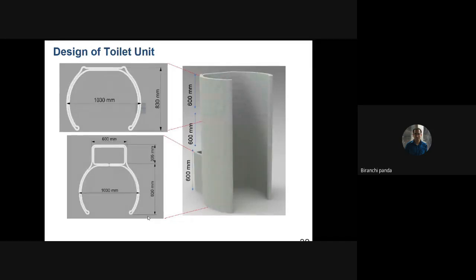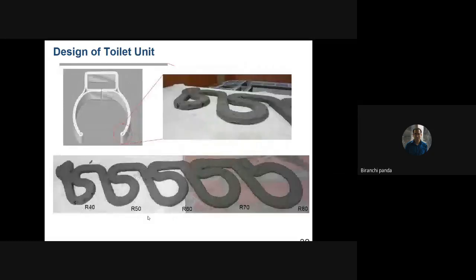We wanted to print a toilet of 1.8 meter height, and when we designed this toilet unit, we found that we have a corner at some section. We wanted to print this corner. There is now the question of what is the best radius. As you can see, for a very small radius, we will have some tearing effect on the layers. If I now increase the radius of curvature, those tearing effects will be nullified.